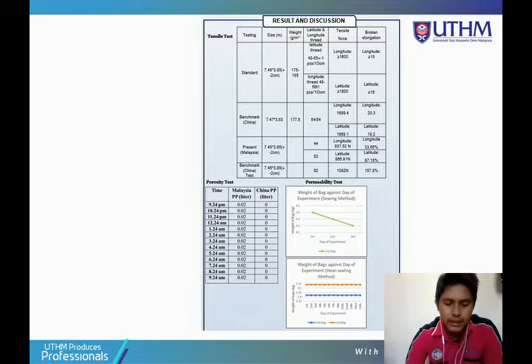For the permeability test, the figure shows the difference between the weight of bags sealed by the sewing method and the weight of bags sealed by the heat sealing method. The weight of the bag decreased gradually every day for the sewing method. Meanwhile, the weight of the bag remains stagnant and shows no change throughout the 2 months period for the heat seal method.